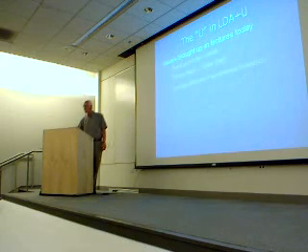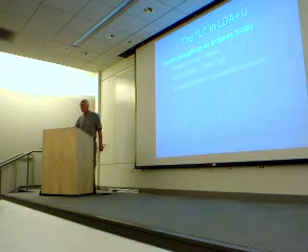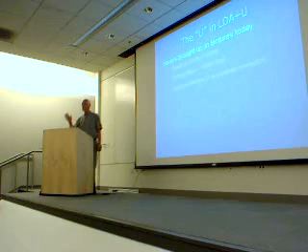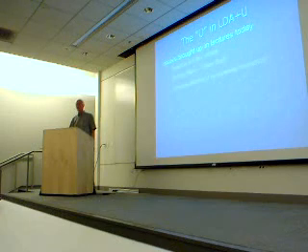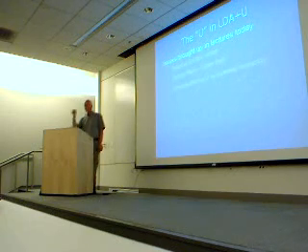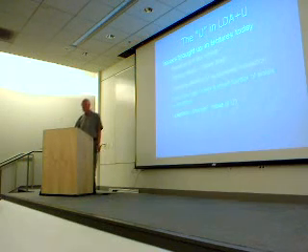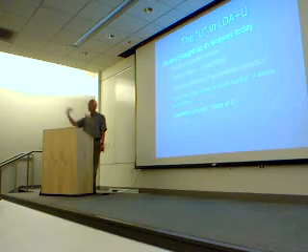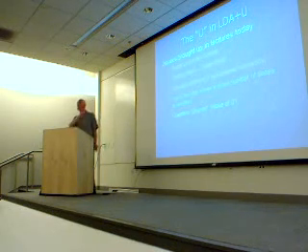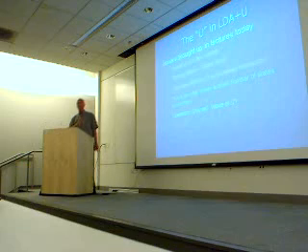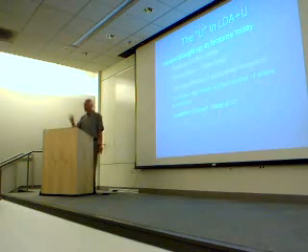And if you want to deal with how large the effects are, you need to calculate this U, as it's the screened interaction, screened by the other electrons, and that's not an easy problem. You have to identify the states, you have to calculate the U, and this is the step where you say a small number of states is interesting, and where you can do something with it, and you have all these questions of uniqueness, choosing the states, and what are these values of interactions.